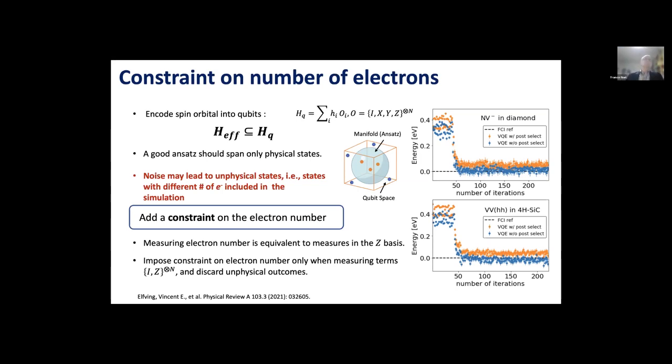Yeah, but the states that originate from the presence of the defects are states that you cannot describe by just using one single Slater determinant. They are not single reference, they are strongly correlated, so you have to do something else. So we use the screening to define the effective Hamiltonian, but then we treat the effective Hamiltonian by describing the active space with a quantum chemistry method that can account for the strong correlation of the defect.